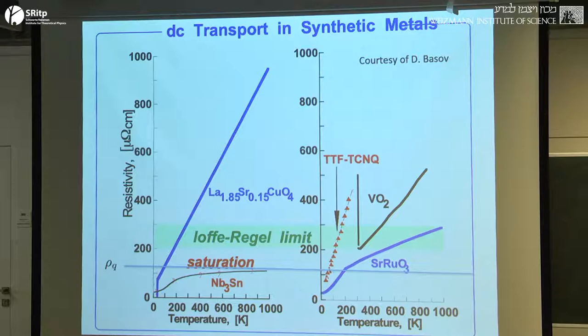And maybe we can use some of the usual machinery of theoretical physics. But we made the following argument, which isn't a slam dunk, but also isn't totally stupid. We said, if there are no quasiparticles up here, and if the resistivity is dead linear in temperature without any sign of a crossover, then probably you better not use a quasiparticle description of the system, even here, just above TC. And that's very upsetting, because that means that you have to invent a totally new approach to the theory of superconductivity. Okay, so that's the controversial thing that we said, and I'll come back to that on the basis of calculations that Erez and Yochai have done.